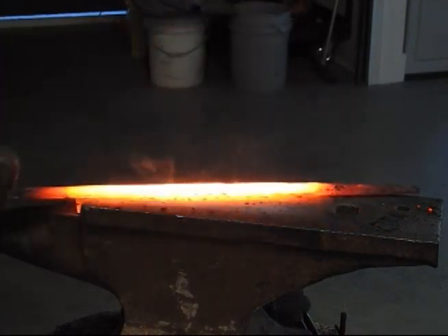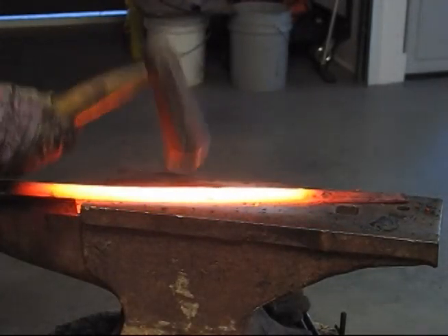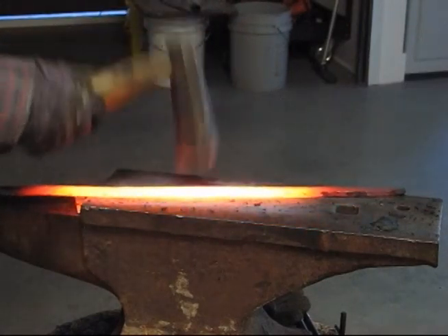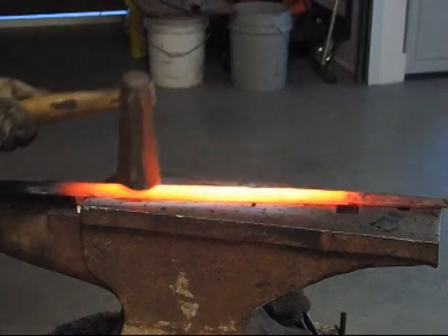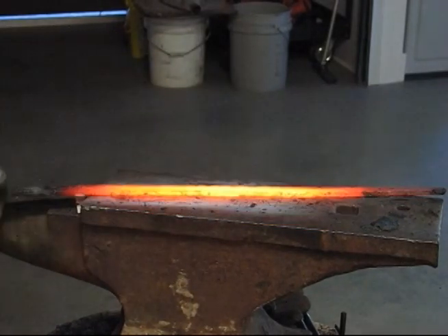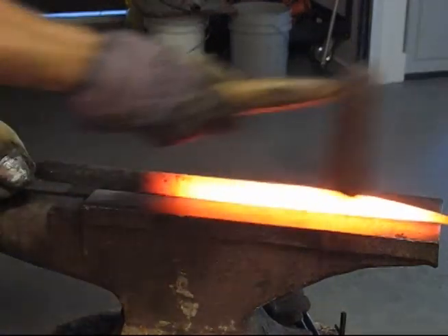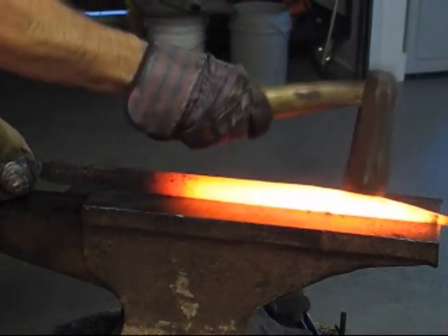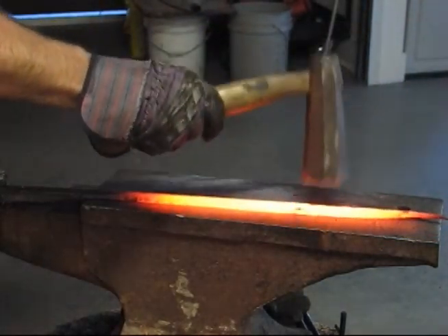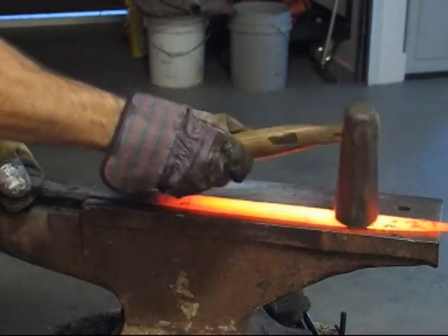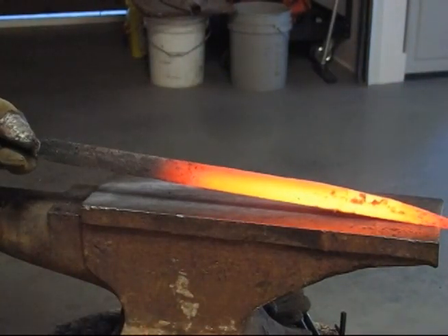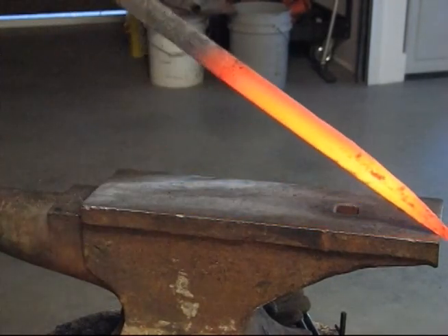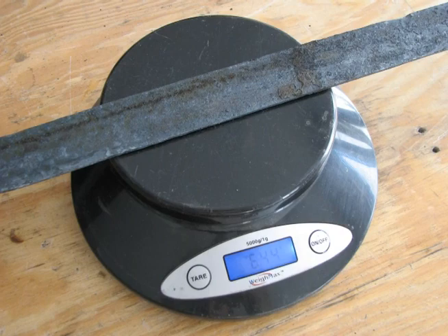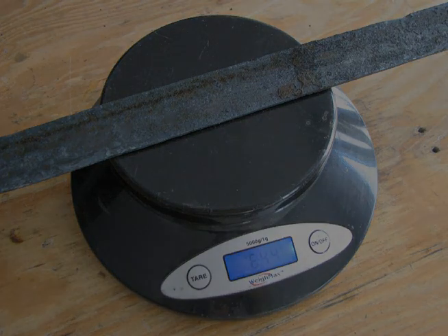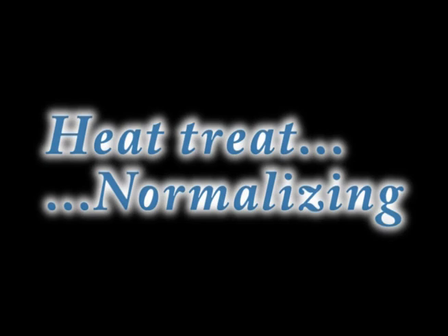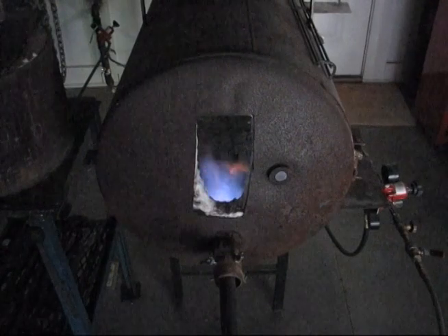The last forging step is to straighten the blade. 30% of the mass was lost during the forging of the blade. Before any grinding is done on the forged blade, the heat treating process begins. The first stage is to normalize the metal.